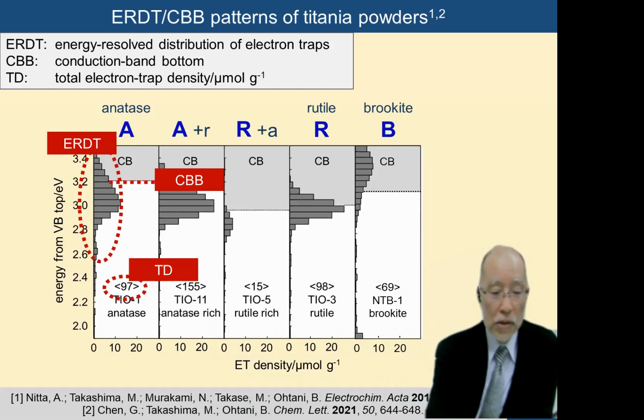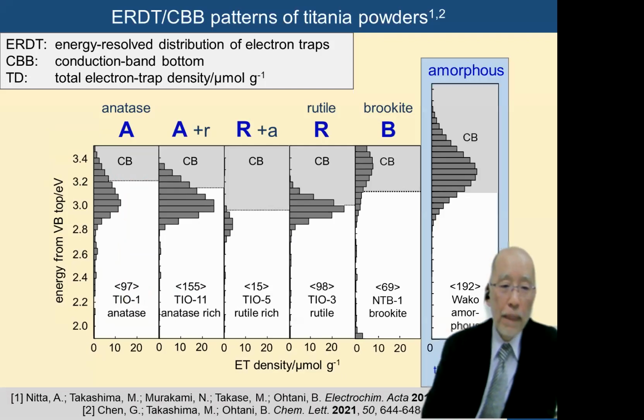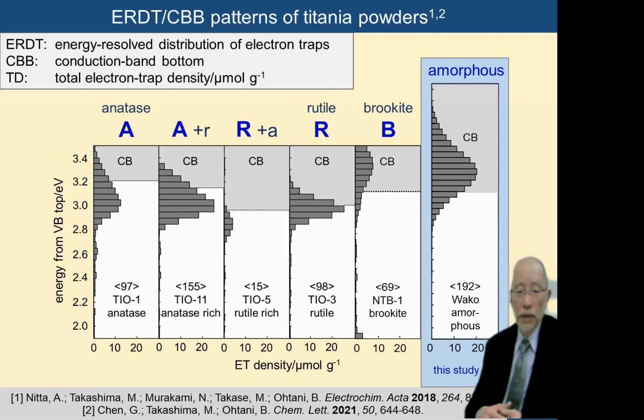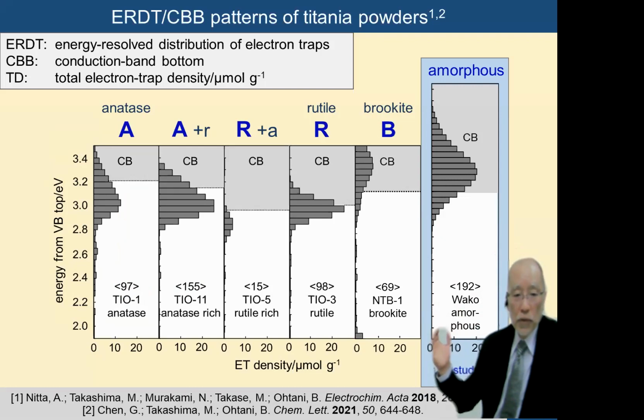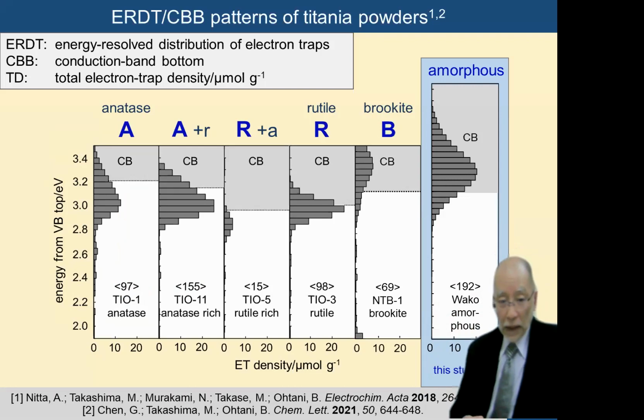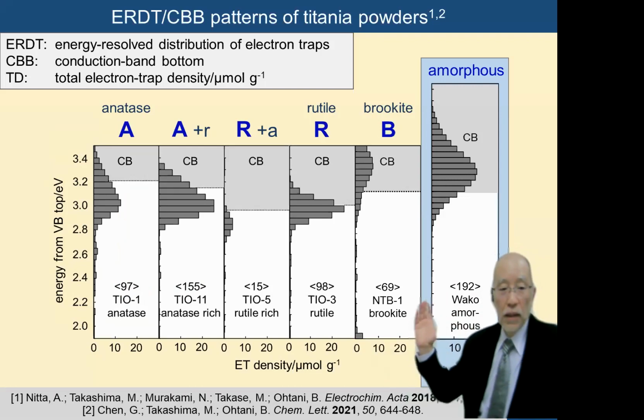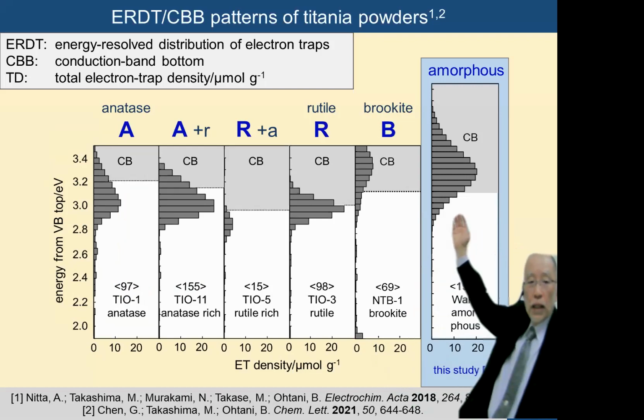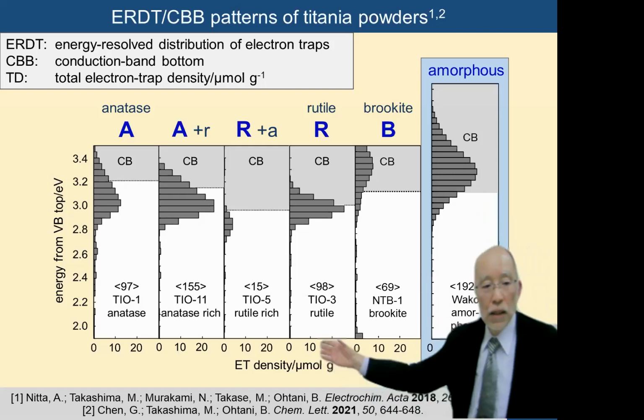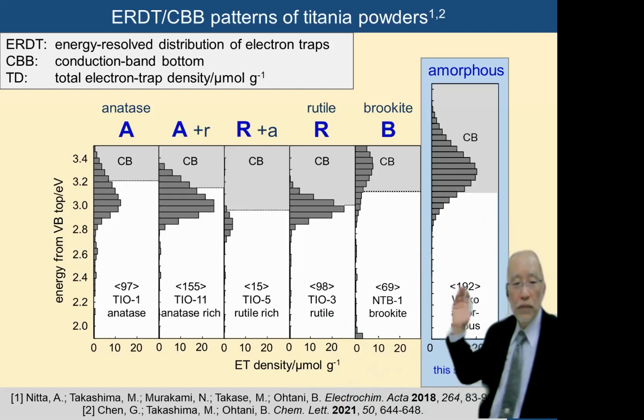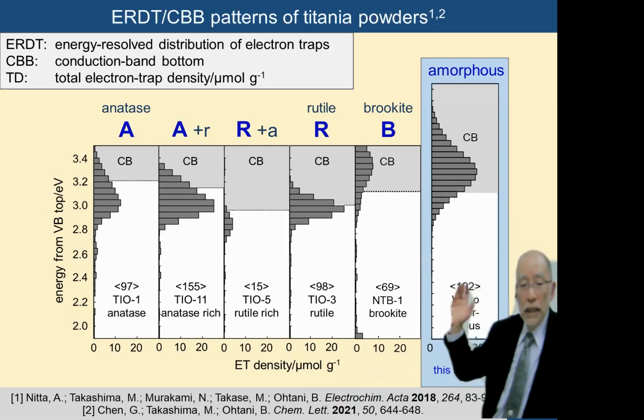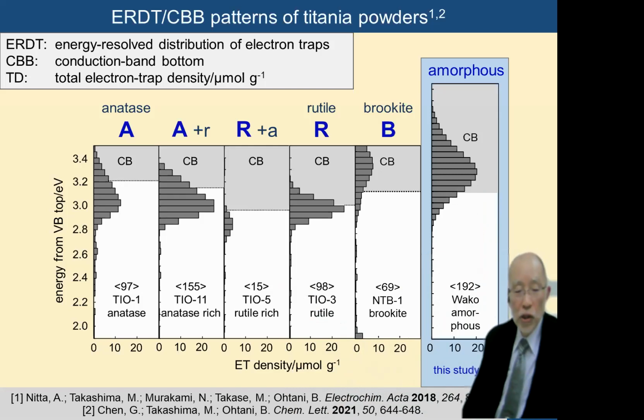And the important point is amorphous material. It was previously available. Now it is impossible to get, but previously we could purchase amorphous titanium oxide. The composition is determined to be TiO2, but no crystalline phase, no peaks in XRD. But the composition is TiO2. That can be amorphous titanium oxide. And this also shows the similar ERDT pattern, although the position is a bit higher than the other crystalline material. But even if that is completely amorphous, no crystalline phase, the ERDT and CBB pattern can be measured by using this technique.